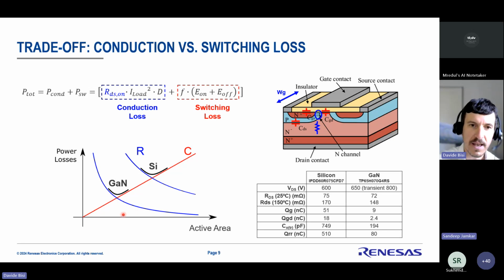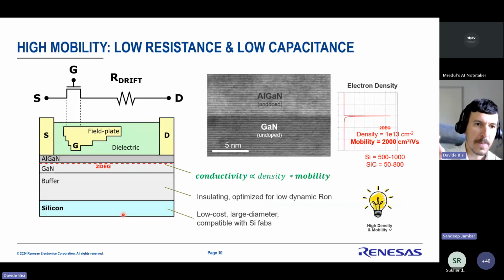Now I can try to go to the next slide. And so this is the GaN device architecture. I'm sure most of you are already aware of it. It's a lateral transistor, so we have source, gate, and drain at the top. And the transistor is grown on a foreign substrate, which can be silicon or sapphire. Silicon for a 6-inch wafer, very high diameter wafer, low cost, very high manufacturing capabilities. Of course, there's a buffer layer to isolate the active area from the silicon.